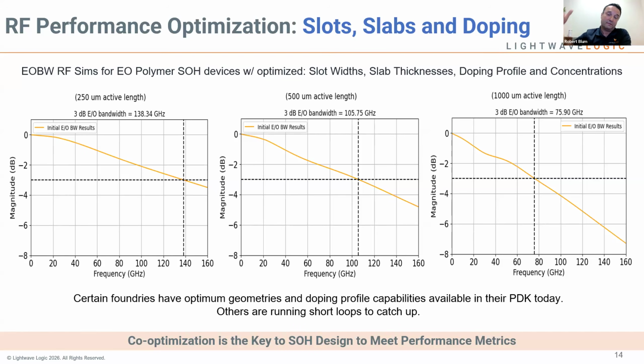But also what is very nice with these types of modulators is that there's no rapid roll-off in the frequency, so it's quite linear. So for example, your 6 dB point is around 135 gigahertz or so. So this is very much workable for a lot of applications. And our VπL, which I didn't put on this slide here, is less than 1 volt millimeter.